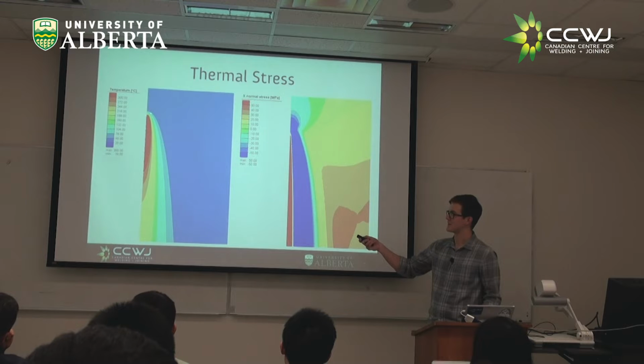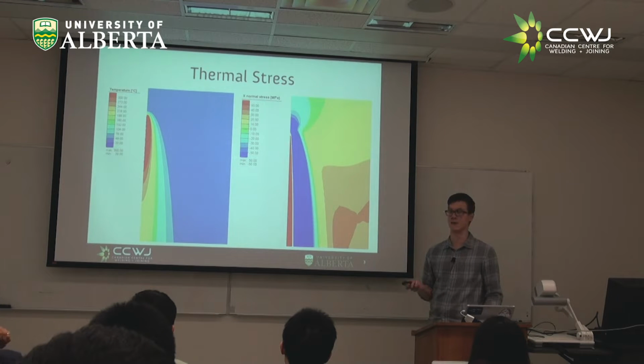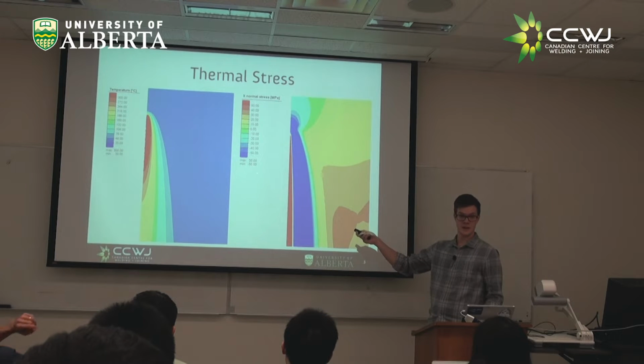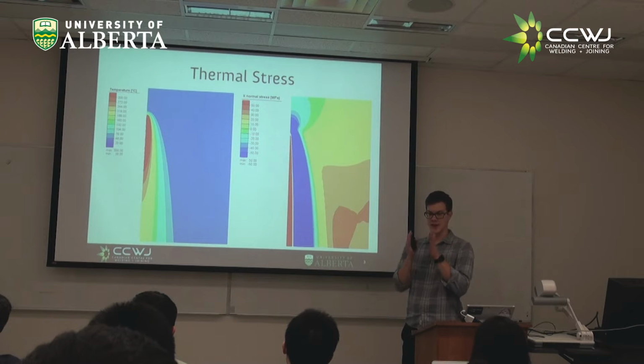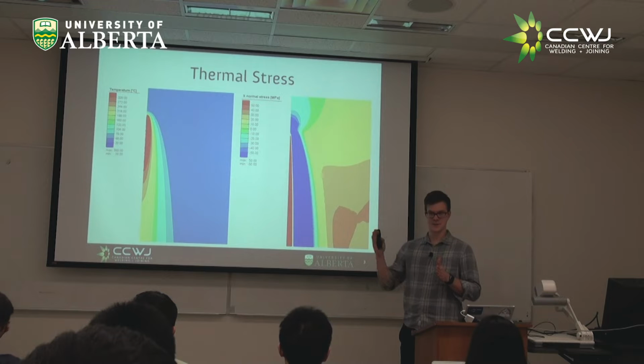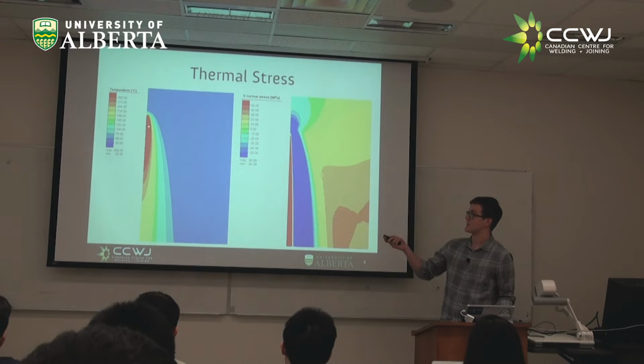Now one thing you notice here is the temperature field in this direction is completely different than in this direction. And this is typical for the fast-moving heat sources we have in welding, where typically your thermal gradients are going to be really, really huge across the plate and comparatively small in this direction. So that means as each element of the plate wants to expand, the elements next to it are going to be expanding at a different rate, they're going to be at a different temperature, and they're going to be stopping those elements from expanding. And what you see resulting from this is in this region where you have really high thermal gradients, you get high stresses. And this is typical of what you'd see for stress development while you're welding.